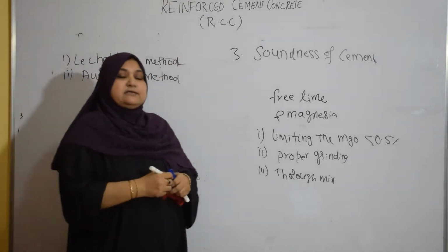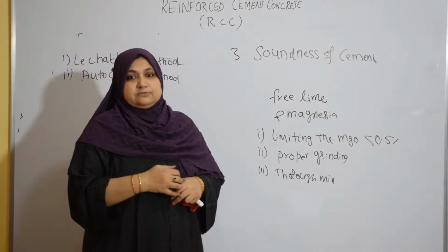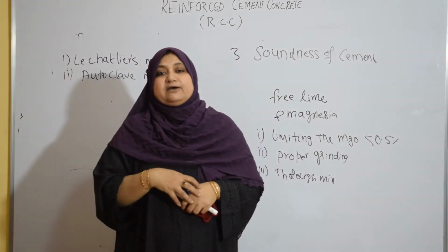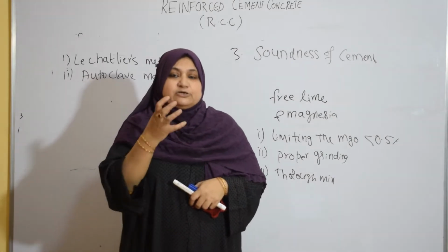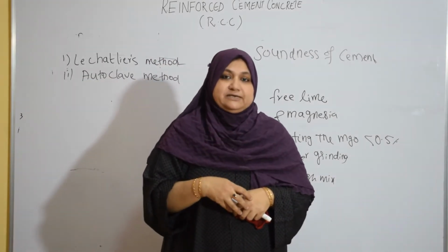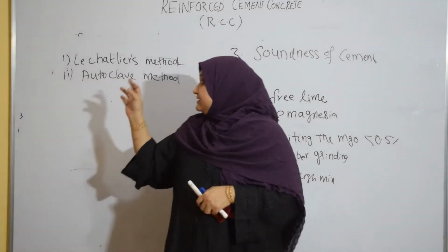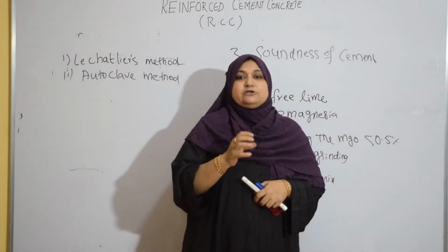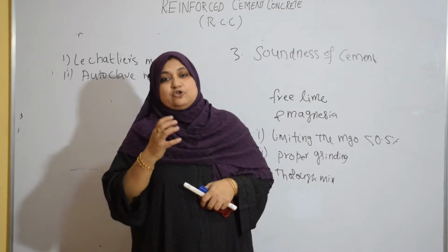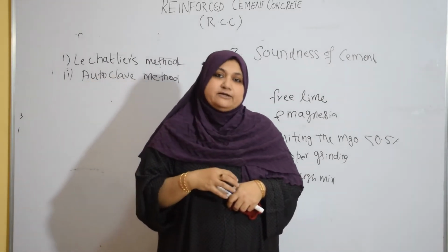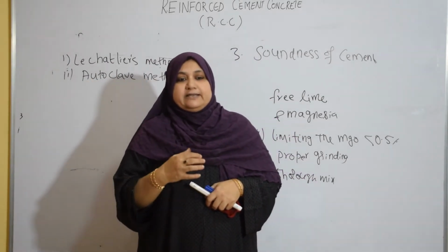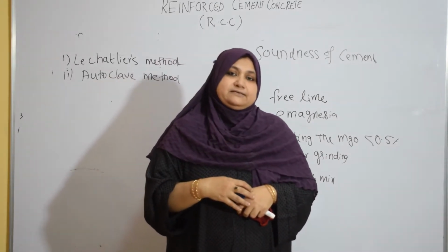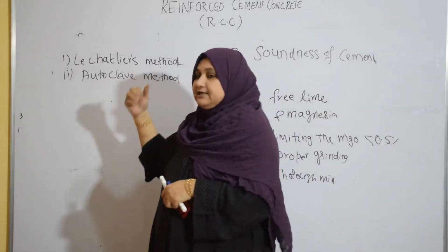What we do is the hardened cement cube, we boil it for a fixed time. Okay, so it expands. That expansion is measured. That is the Le Chatelier's method procedure. In short, I have said. Hardened cube of cement paste is boiled for a fixed time, so that any tendency to expand is speeded up and can be detected. So that is the Le Chatelier's test.